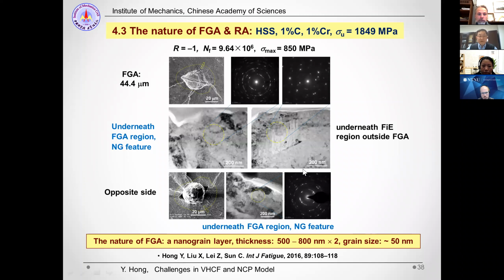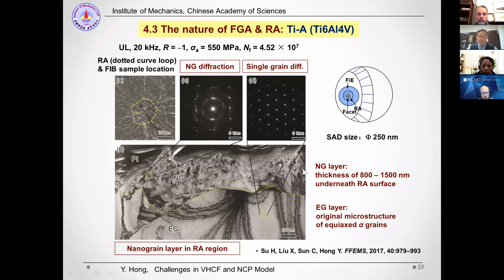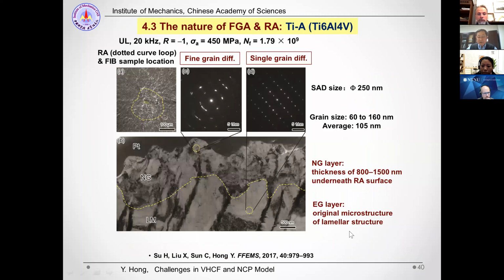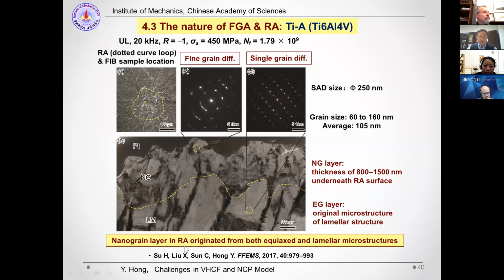And for the case of titanium alloy, we also observe the fracture surface of FGA initiation region by a FIB sample to reveal that the thickness is between 800 and 1500 nanometers. And also the microstructure is refined, and this is equiaxed microstructure. And also for the microstructure of lamellar feature, the fracture surface is also refined. So for titanium alloys, the FGA region is a nanograin layer, no matter whether the microstructure is equiaxed or lamellar.